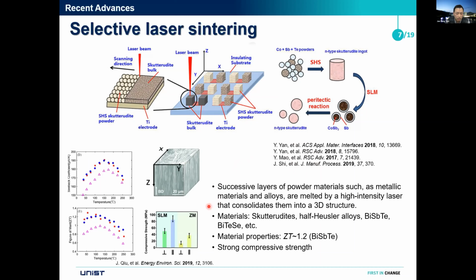And in some cases, the material property ZT value increased up to 1.2 in the bismuth antimony telluride case. This is comparable to the material synthesized by the traditional process. Also, in this process, the material is quite dense, so this material has quite strong mechanical strength. The issue in this process is the very high, very expensive price of the equipment. And also this equipment is very difficult to customize.